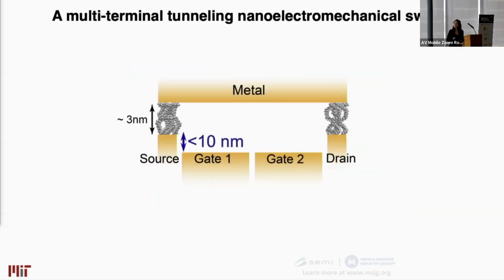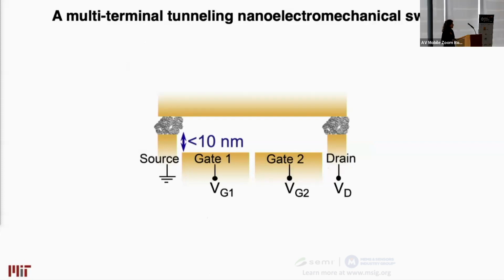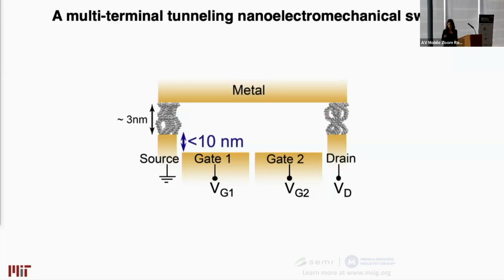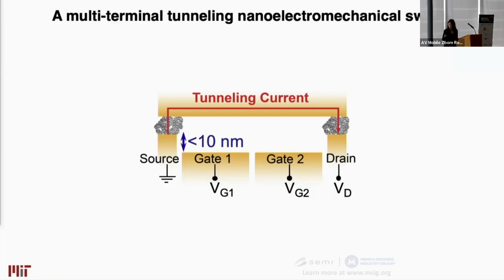So this is a particular design that we developed and fabricated. In this particular example, the gate electrodes are used to electrostatically actuate the switching gap, modulating the tunneling current. And of course, as the voltage is removed, the process can be reversible. In this particular example, it is quite important to have the surface topography that you're seeing here in order to be able to keep your actuation voltage at its minimum, but at the same time minimize the off-state leakage.